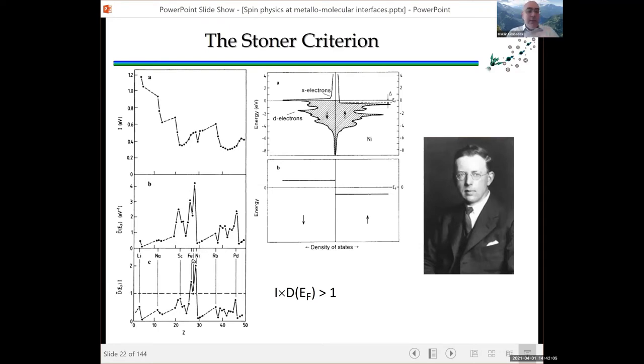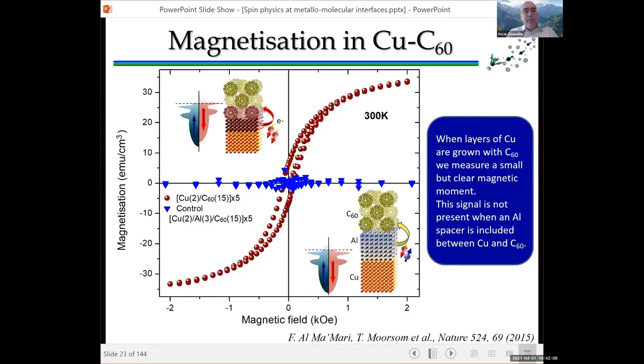We saw that indeed, if we had copper and we put it directly in contact with C60, we can have a hysteresis loop and induce magnetization. If we break the interface between copper and C60 with aluminium, then that emergent magnetization disappears and we go back to a diamagnetic or paramagnetic response, depending whether we use copper or manganese.